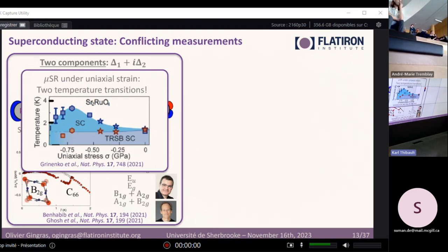The final experiment here that highlights two components is that, if you have two degenerate components and apply a perturbation like uniaxial strain, you would expect to lift this degeneracy. In particular, you would expect a first temperature transition into the superconducting state, and then a second one into the time reversal symmetry breaking state. And this is exactly what is observed in μSR. So this is an interesting and coherent picture that there are two components.